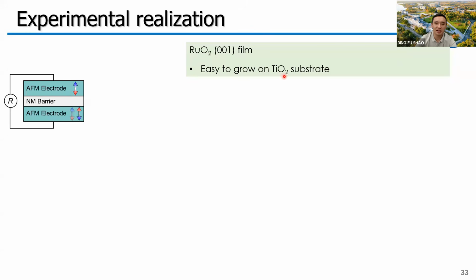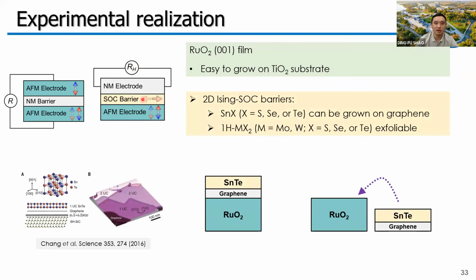Since ruthenium oxide and titanium oxide are very easy to grow, we can expect high quality epitaxial antiferromagnetic tunnel junctions using these materials to observe the TMR and STT driven by Néel spin currents. And for the tunneling anomalous Hall effect, the barrier material we propose, tin telluride, although it cannot be exfoliated from the bulk material, can be grown on graphene. So we can put graphene on top of ruthenium oxide and then grow tin telluride on top of it. Or we can first grow tin telluride and then transfer it on top of ruthenium oxide.